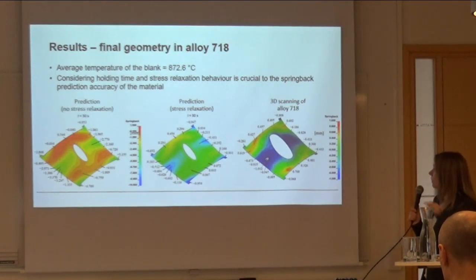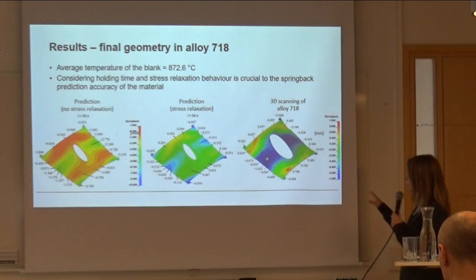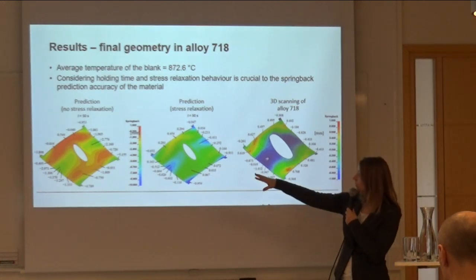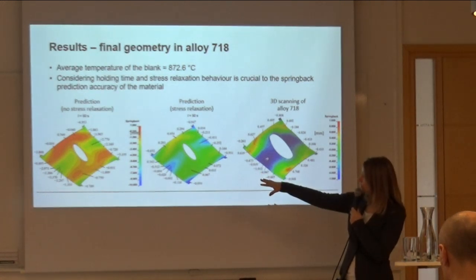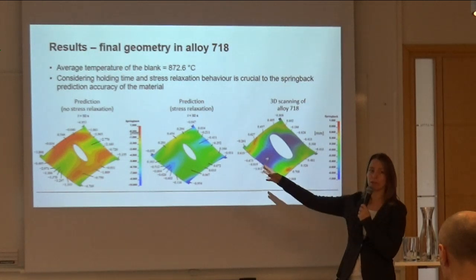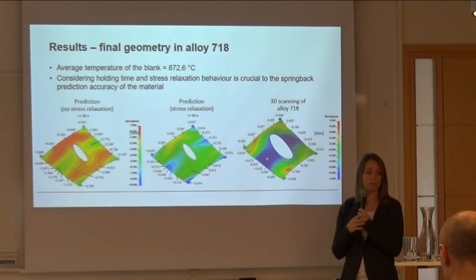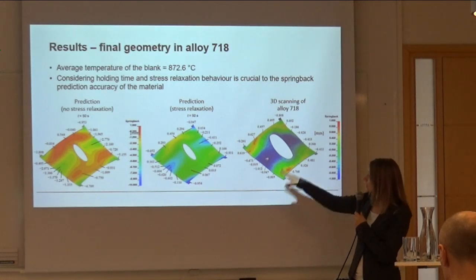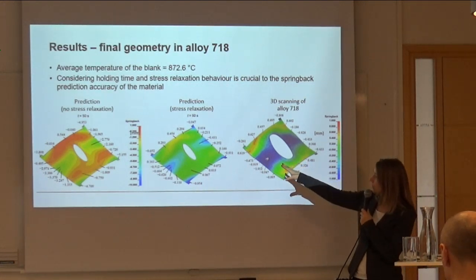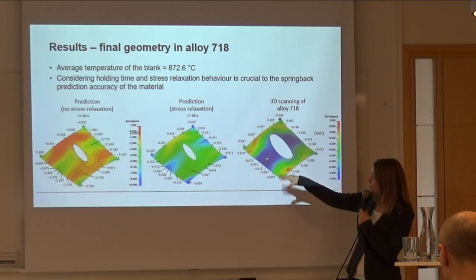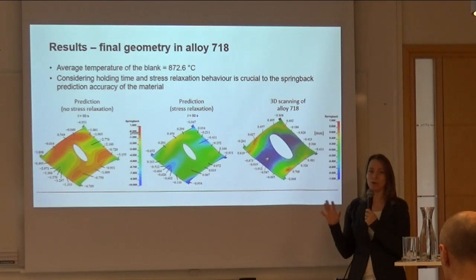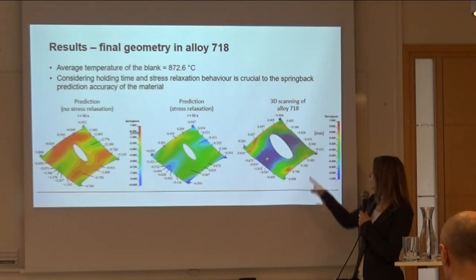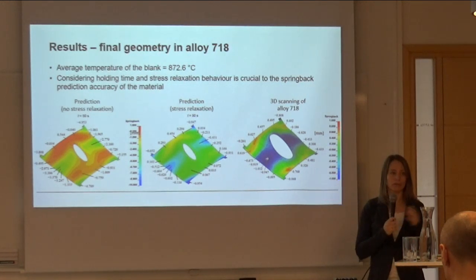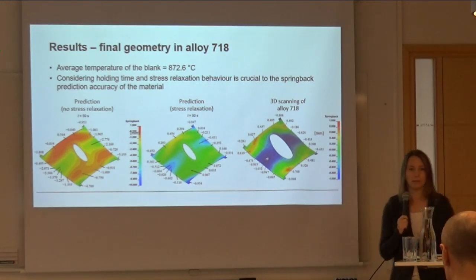In this case, we have also done simulations where we don't include stress relaxation, and in that case we have about 10 millimeters of shape deformation, which is out of tolerance for the industry. If we include the stress relaxation, we are at a shape deviation of approximately 1 millimeter, which is within the tolerance that the industry puts on the part.